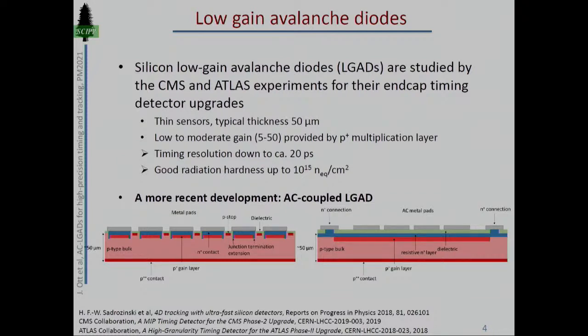As the name says, their main characteristic is a low to moderate gain compared to, for example, SIPMs, of the order of 5 or 50, maybe sometimes up to 100, provided by a p-type multiplication layer. Timing resolution of 20 picoseconds, probably a bit less, can be achieved with the sensors up to date. They've also demonstrated decent radiation hardness up to the order of 10 to the 15.